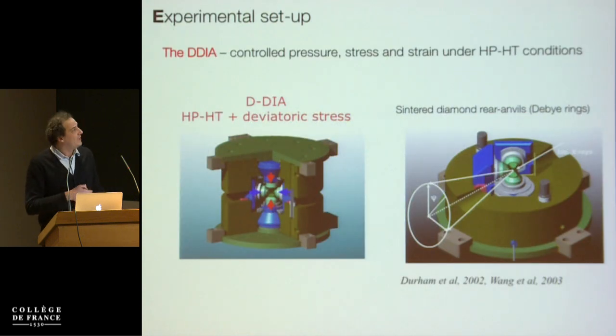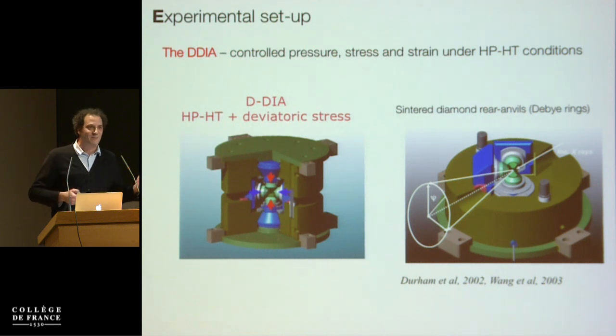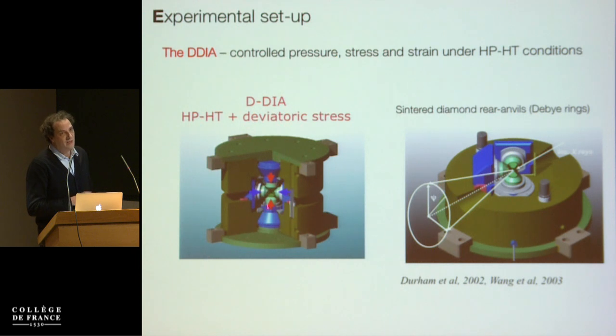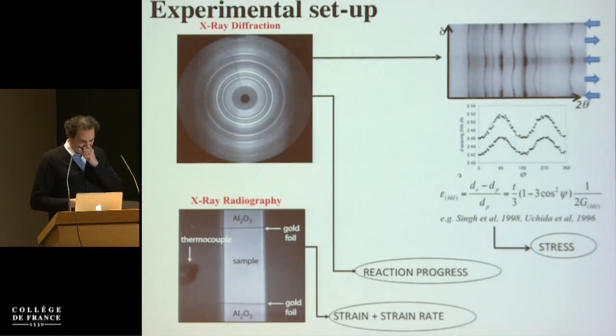So to do that, we took advantage of a revolutionary apparatus that has been developed in the last 15 years, which is the deformation DIA, which is a multi-anvil apparatus. So it's a typical high-pressure physicist apparatus, except these two vertical anvils here can be controlled separately. So you can actually bring the rock or your sample under pressure and then squeeze it. Because the sample is so small, you can't really measure anything ex situ. So what you have to do is to have this machine mounted on a synchrotron so that you're shooting X-rays through the sample and using X-rays to image the sample. And I will show you the role of the X-ray.